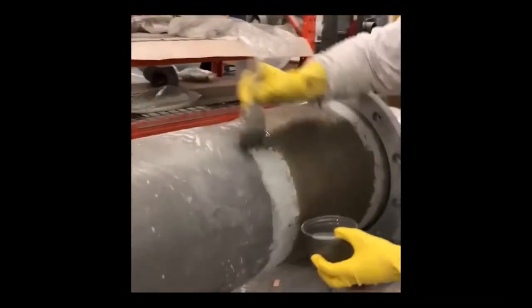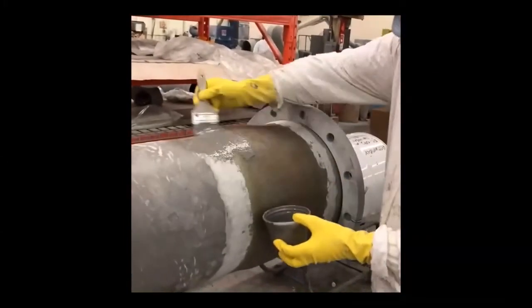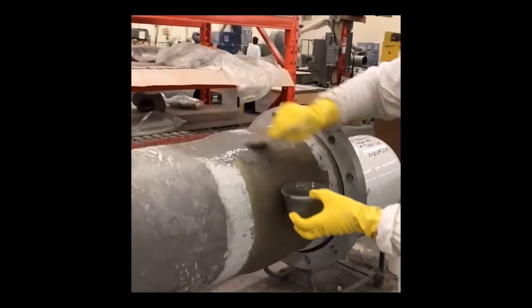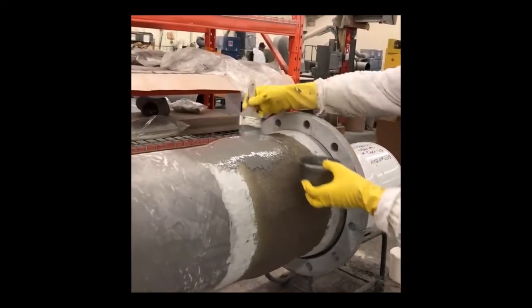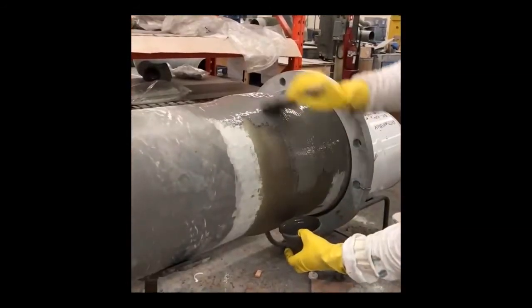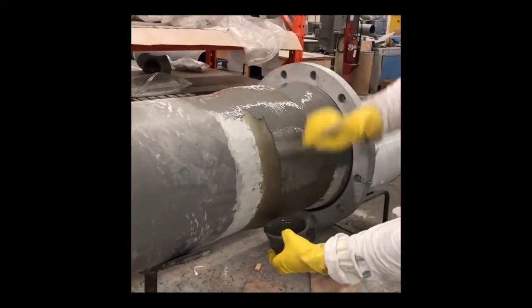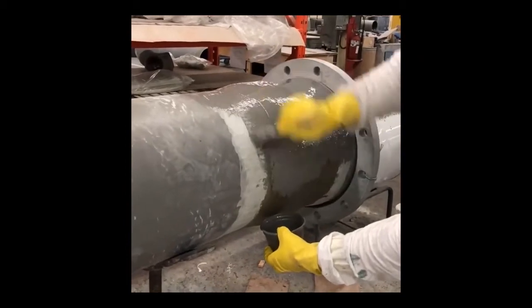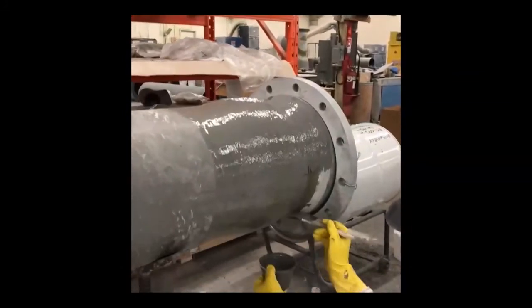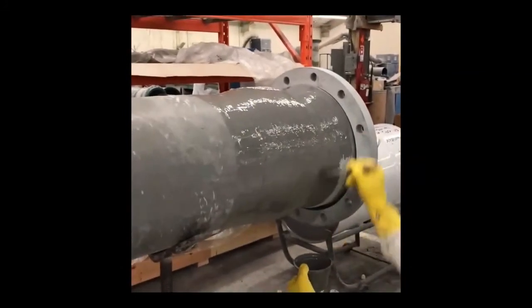So then once it's cured, what the technician is doing is applying again a wax top coat. In this case, it has gray pigment. He applies that all over the sanded surfaces. So the layup and the areas he sanded past. You notice he sanded a little past the layup. So he applies that all over the sanded surfaces. He's going to allow that to cure.